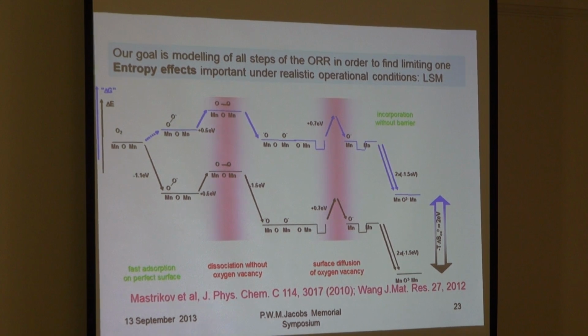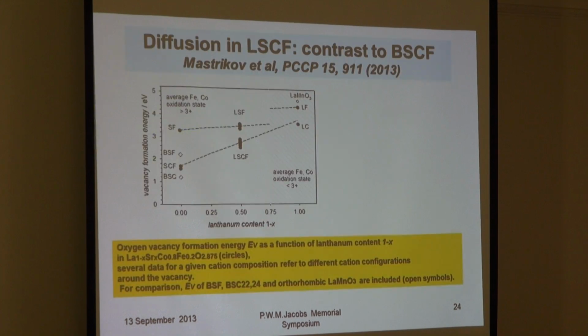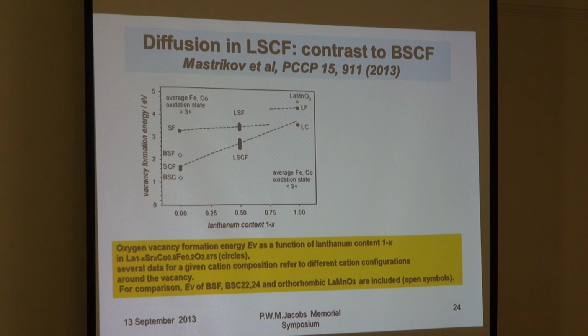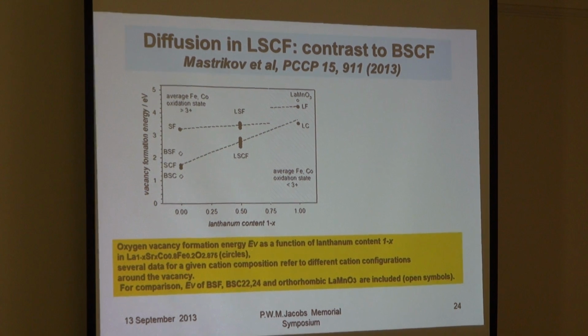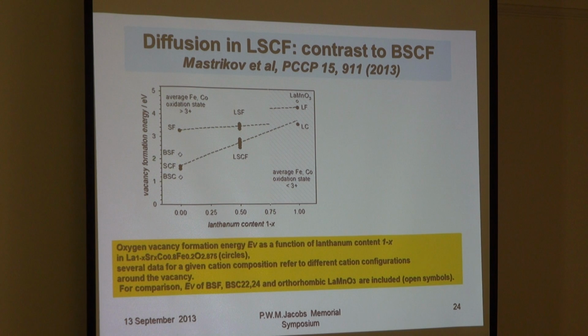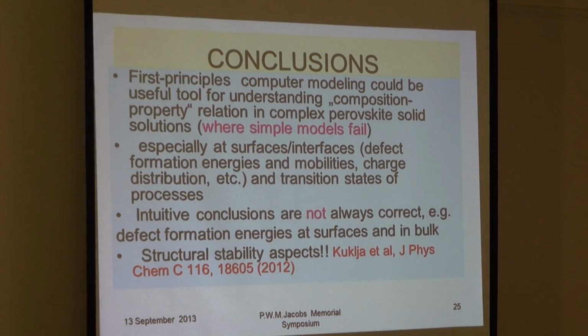which changes the reaction rate very much, and you should be careful about this. And, as a result, we made some predictions for reaction rate for a number of perovskite cathode materials, and also we tried to understand the difference between BSCF, barium strontium, and LSCF, and this big difference. And I mentioned that the difference is also in particular because we have different charge transfer for oxygen in the migration phase. And this is why the use of pair potentials in this delicate modeling turns out to be quite limited. So probably I should start to finish.